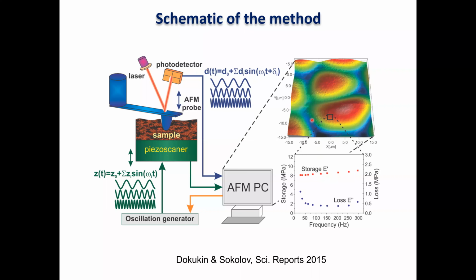We can use this information, and we extract storage and loss modulus at, for example, in this case, 10 different frequencies. And this is actually a picture of plant cells from pumpkin. It's the surface of a pumpkin seed, essentially. So at each pixel, you have recorded this storage and loss modulus. So 10 and 10, 20, and you have also extracted the static modulus. So 21 moduli essentially at each pixel. This, for example, is 150 by 150 pixels.